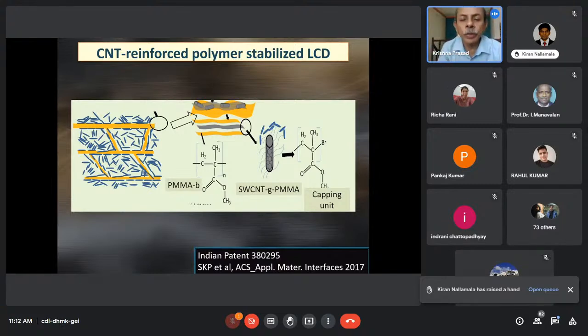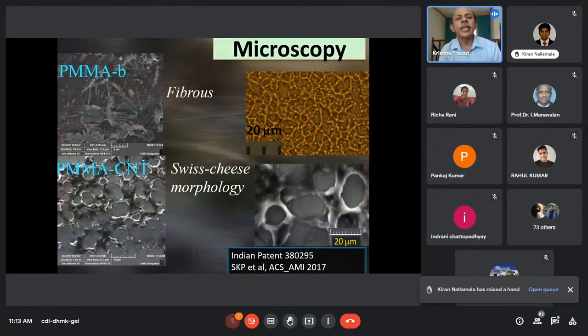And that we could do with a very interesting kind of single-walled carbon nanotubes, which are grafted with PMMA that was prepared by our collaborators in Central Leather Research Institute in Chennai. And we chose PMMA as the confining matrix, and by suitable chemistry that exists on the CNTs, now we could marry the CNTs and the base PMMA and confine the CNTs only into the polymer regions. And that resulted in an architecture very clear of that of a similar PDLC kind of system.